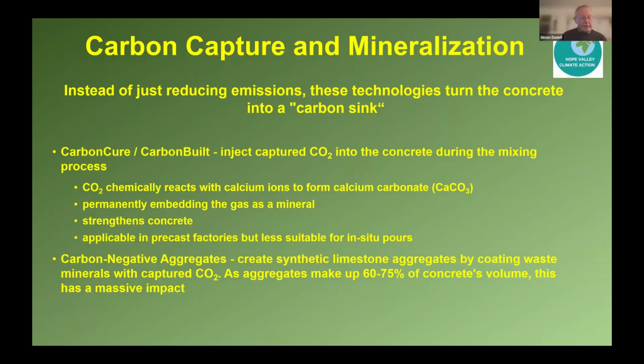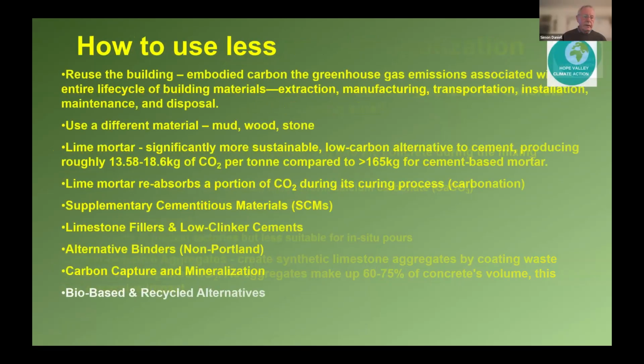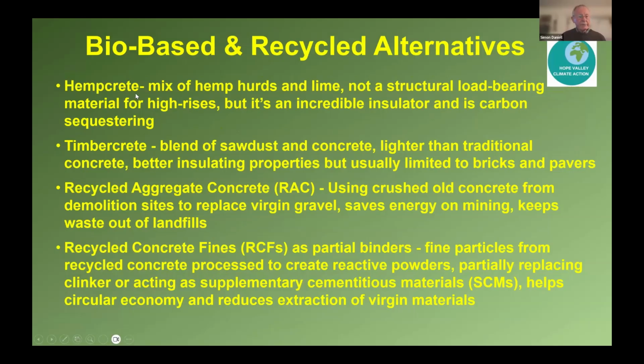You think of the concrete pipes, all the units that go in to make flooring, etc. So that's another way. Another clever thing they've done is they've taken lime aggregates and then coated waste with minerals with captured CO2. And that's another way of reducing or capturing the CO2 to reduce the CO2 that's being produced. And then we've also got bio-based and recycled alternatives. You can see there's a lot of work going on here. Hempcrete, great for insulation retrofitting. It's not really structural, but it's a great insulator and it's good for carbon sequestration. Timbercrete using sawdust, again, limited to bricks and paving.